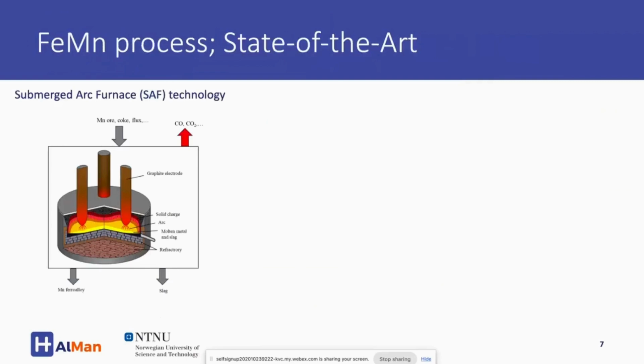Next slide, please. Here you see the state-of-the-art technology that we have nowadays around the world in different countries for the production of manganese ferroalloys. We have submerged arc furnace, or SAF, technology. In this technology, we use electricity, and we charge manganese ore with carbon in the form of mostly metallurgical coal, and we use fluxes, and we do a smelting carbothermic reduction of the ore, and we produce manganese ferroalloy. There is also slag as a byproduct that usually contains some manganese, which is lost, of course, and we have some gas emissions, CO and CO2 emissions. So CO is later converted to CO2.